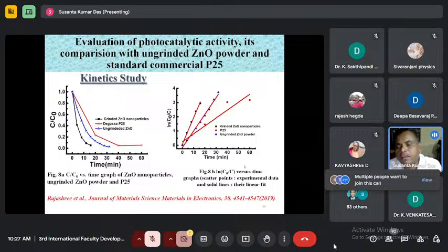And that was also reflected by a more detailed analysis, for that you have to go for plotting a graph between ln C0 by C and time. From C by C0 you can easily find out ln C0 by C, and when you plot this, then these scattered points give the actual experimental results, and the red lines are the fittings. You can see these fitting curves give the slope and these are the linear type of fittings. So these are called pseudo first order reactions, and the slope of this curve generally gives the reaction rate constant. This is the standard procedure for quantifying the photocatalysis reaction constant.